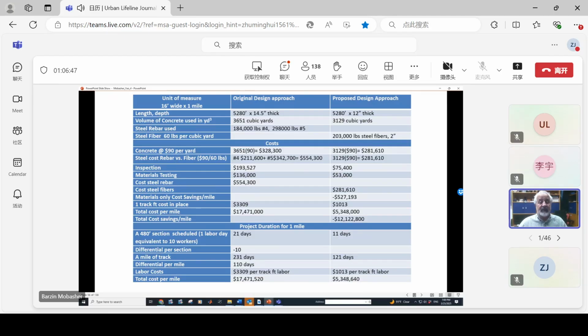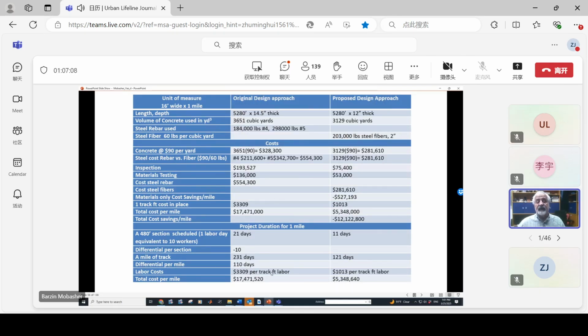It had to be inspected. It had to be delivered to the site. It had to be set up. So it would take approximately 231 days for a mile of the track. When we switched to fibers, we reduced it by more than half the number of days required, and the cost reduced by $12 million. More than 60% cost reduction per foot of the track can be calculated for the total,